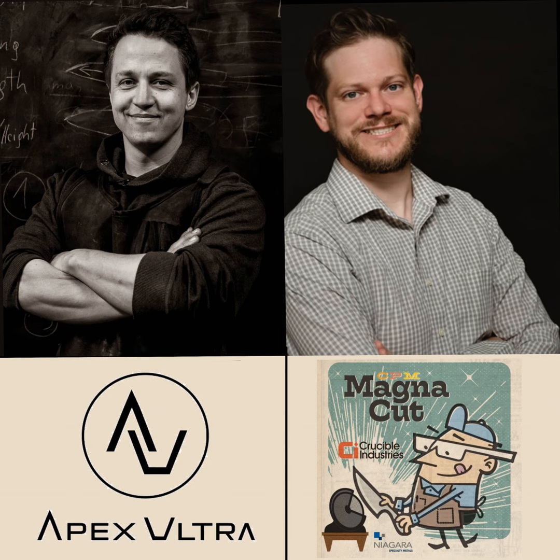I have heard some people say when they have sticking issues, like the foil welding, that when they put baby powder or powder, whatever, graphite, that it helps prevent the sticking. I don't normally have sticking issues, but that could be a reason to put something in there. But usually the foil blows up somewhat, so there's no sticking. I always use foil unless I use X scale, but the envelope you build usually blows up anyway, so there is no sticking issue.